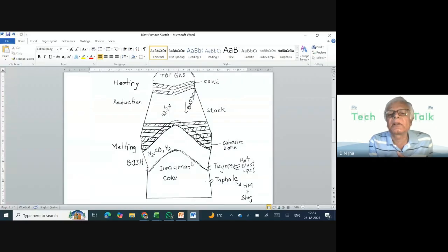However, there are sinks of the heat as well, and one sink of the heat here is the humidity decomposition. And what is humidity decomposition? C plus H2O turns into CO plus H2. So humidity gets decomposed into hydrogen plus CO, and this is a severely endothermic reaction, and therefore it absorbs a sufficient amount of heat in front of the tuyere itself. There is another sink of the heat at this level, and that is breaking of the volatile material. So once the volatile material breaks, it also consumes some amount of heat.